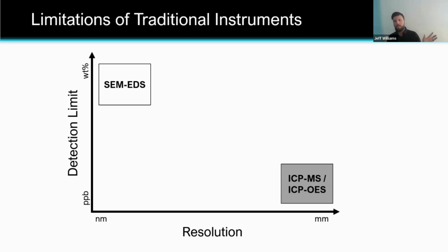On the other side of the equation, we have ICP-MS, right? So very, very good detection limits down to parts per trillion in some cases and parts per billion level detection limits. Still some limitations on what elements you can see, but you are taking that sample and you're digesting it in acid, right? So I put this kind of on the resolution of millimeters to centimeters because you're taking some amount of material, digesting it, and you're getting one data point out of it. And you can see there's kind of this gap, and there's obviously a lot of other tools we could talk about here, but I just think that this frames it super nicely.